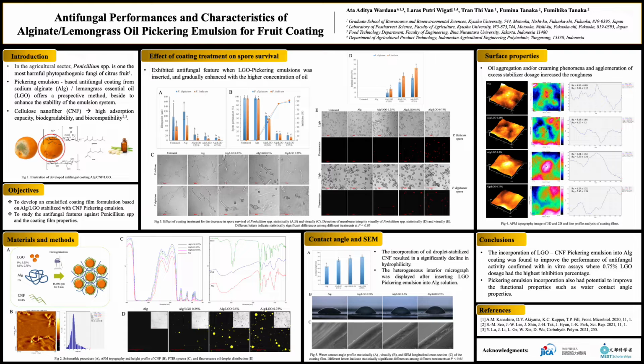The microstructure of each coating sample was observed using CLSM, shown in figure 2D. Obviously, the emulsion droplets were uniformly distributed in the photograph, indicated with yellow color, and displayed a spherical shape. Moving on to the results, Penicillium digitatum and Penicillium italicum are considered the major cause of fungal decay found in fresh fruit commodities. Hence, in this work, the inhibition of spore germination and survival were investigated. Visually, as seen in figure 3c, Penicillium italicum spores were more susceptible in comparison with those of Penicillium digitatum. Statistically, compared to control and alginate-treated spores, the antifungal features of alginate essential oil increased dramatically, and the inhibitory effect continuously enhanced by 88.28% for Penicillium digitatum and 91.94% for Penicillium italicum when a higher essential oil level of 0.75% was added.